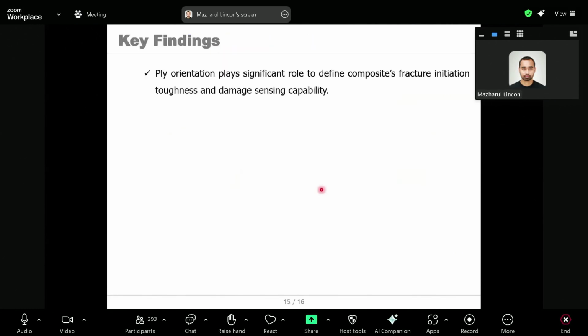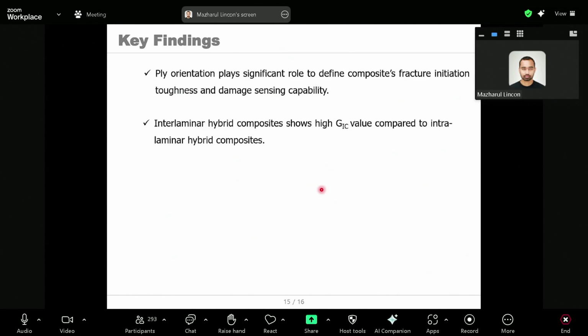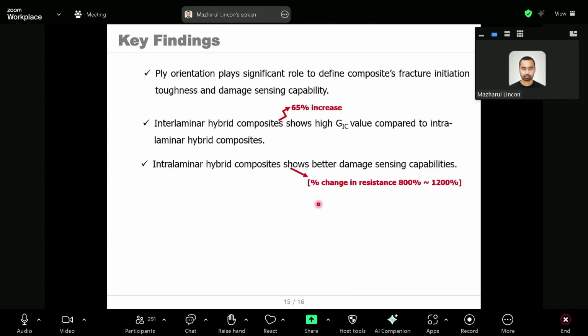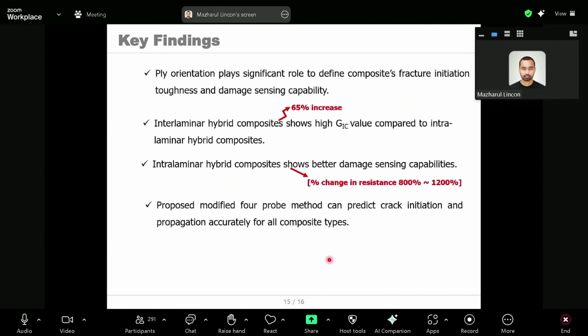The key findings of this research show that ply orientation plays a significant role in defining composite fracture initiation toughness and damage sensing capability. Interlaminar hybrid composite shows high fracture initiation toughness compared to intralaminar hybrid composites, around 65% increase, while intralaminar hybrid composite shows better damage sensing capabilities, around 800 to 1200% change in resistance. The proposed modified four probe method can predict crack initiation and propagation accurately for all composite types.